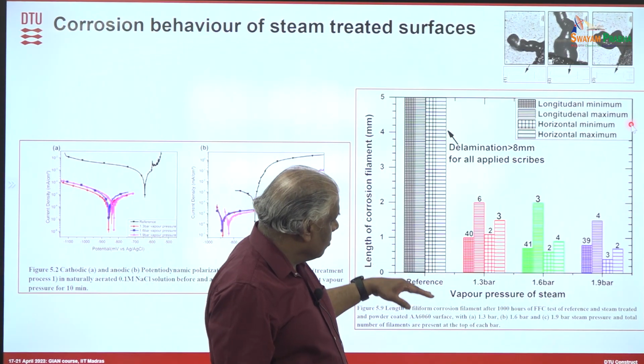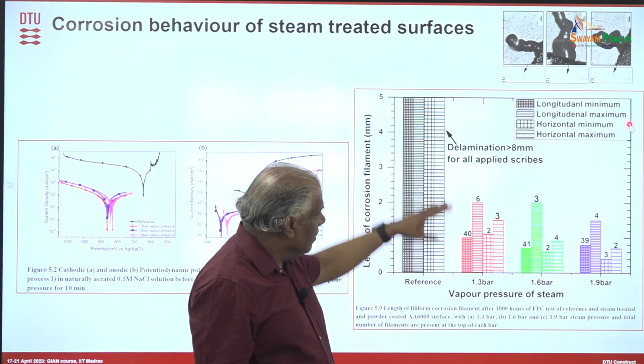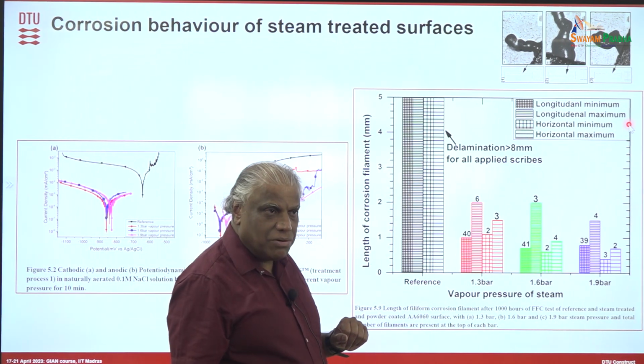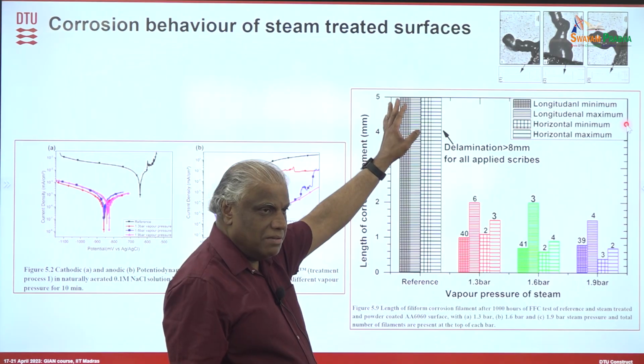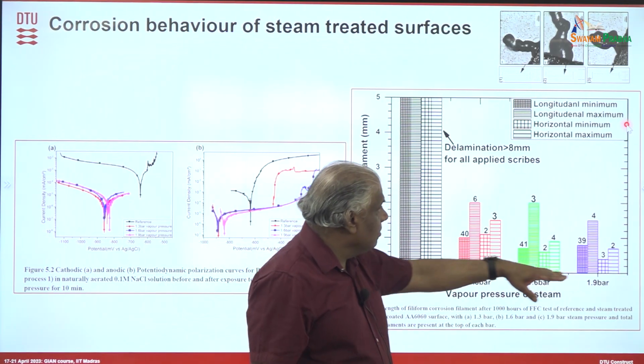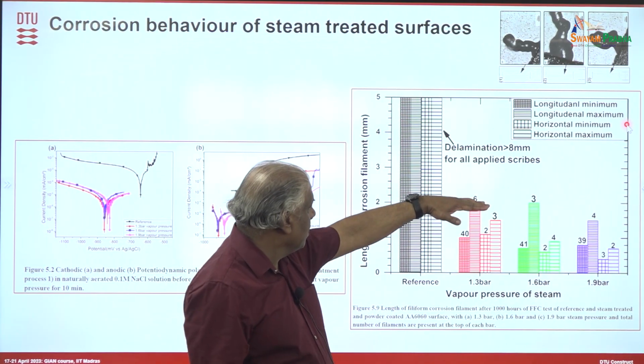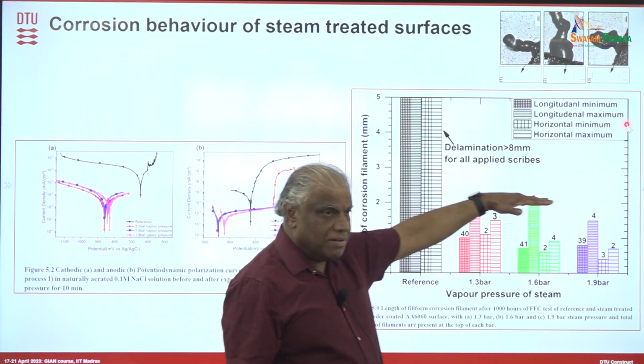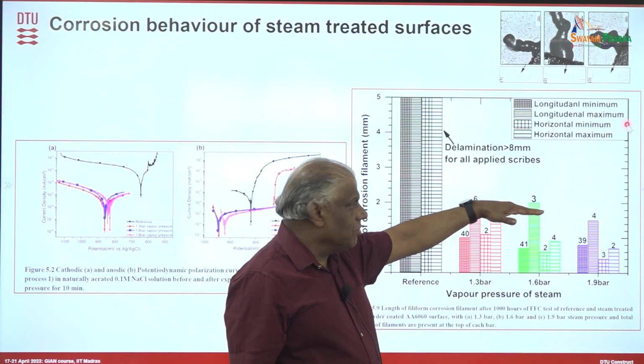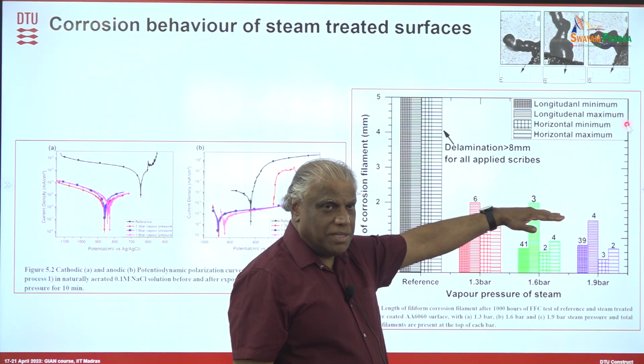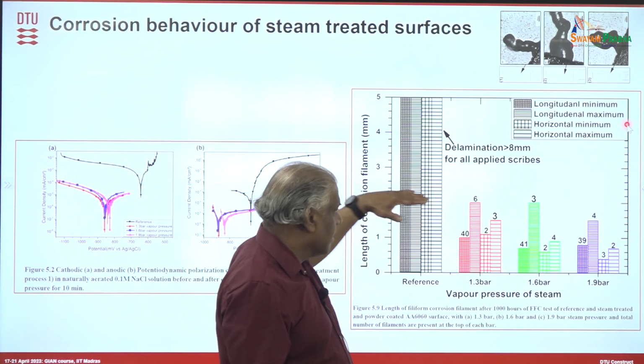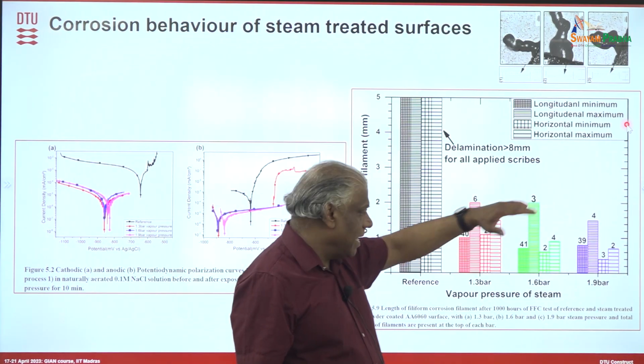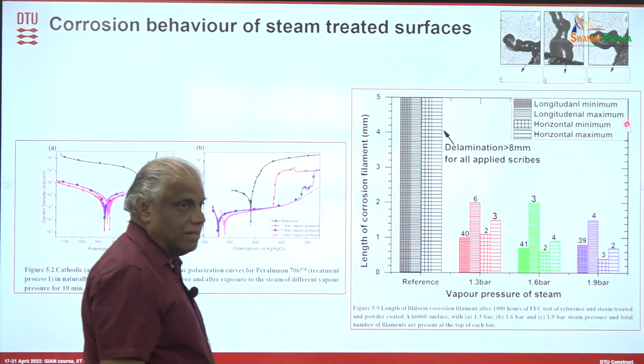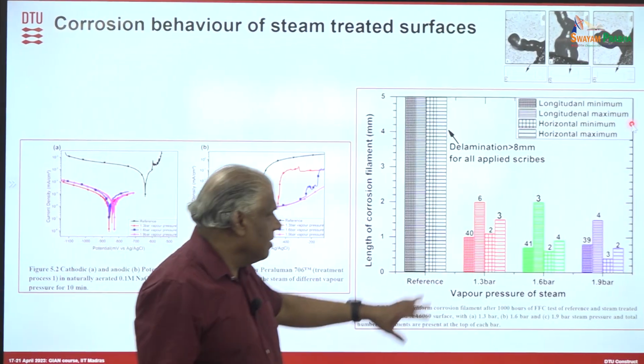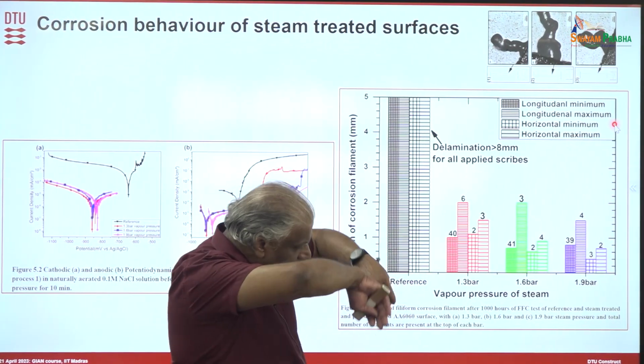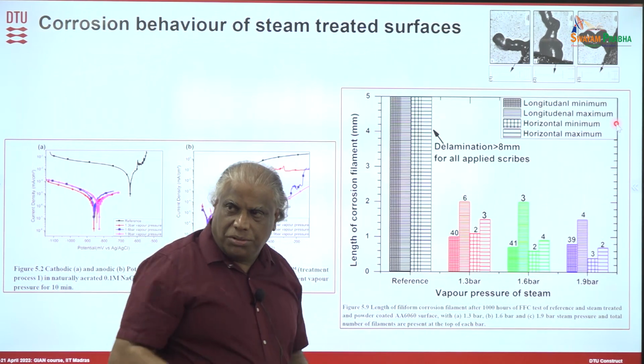So then we did that. You can take the reference with just a paint without any conversion coating, it immediately failed. But you can see here that with this one, you have a much lower level of this filament growth here, and so it is good. It's working well. I don't remember exactly what the cutoff limit is here, which they think, but I think it is coming somewhere later. But it is working, so that way it is having good adhesion. It is not allowing the corrosion to penetrate and occur. That's what you see here.